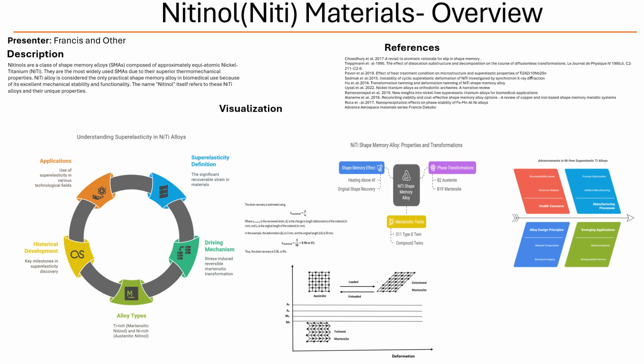And it's interesting, research has shown that if you make the grains within the SMA really, really small, like down to the nanoscale, you can actually increase its resistance to this dislocation slip. There are techniques like equal channel angular extrusion, or ECAE, that can be used to achieve this grain refinement. And they've been really successful in alloys like NiTi. It's basically squeezing the material through a die with specific angles to create this ultrafine grain structure.